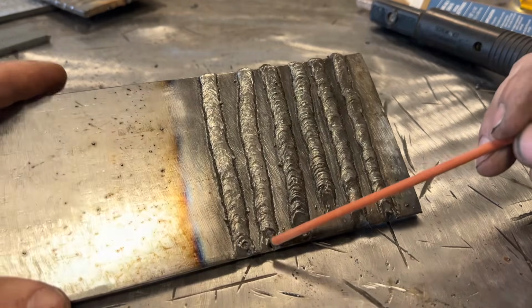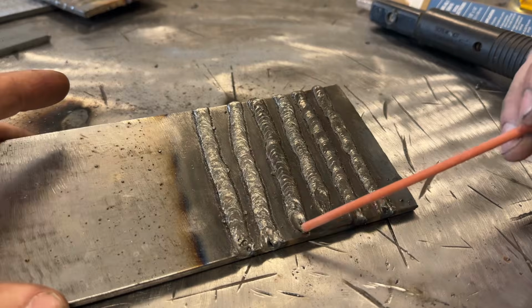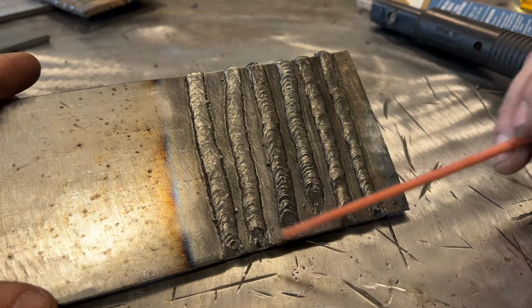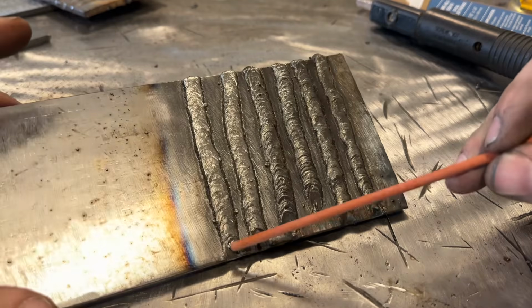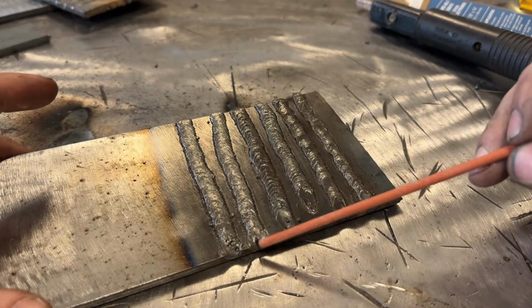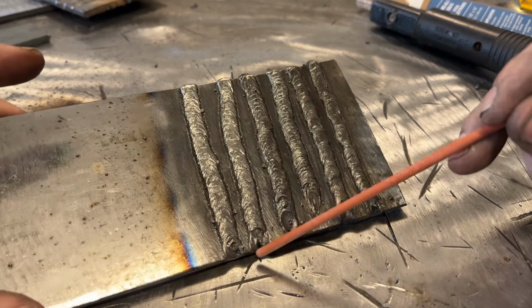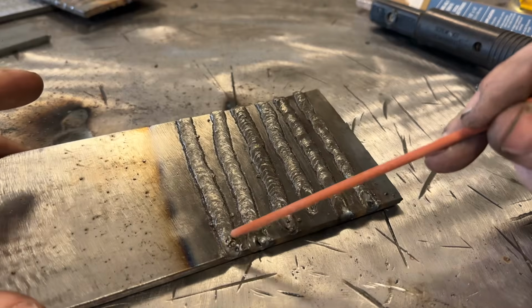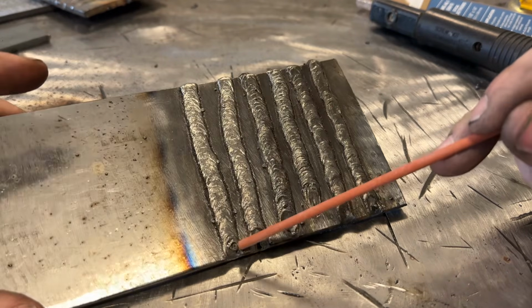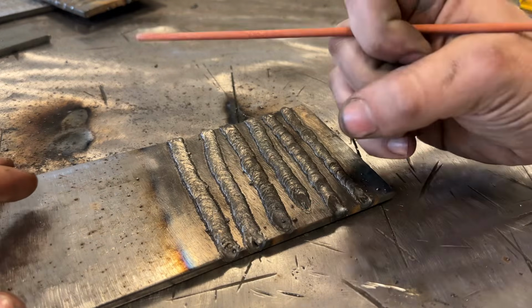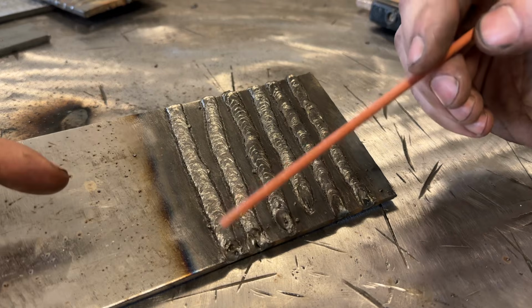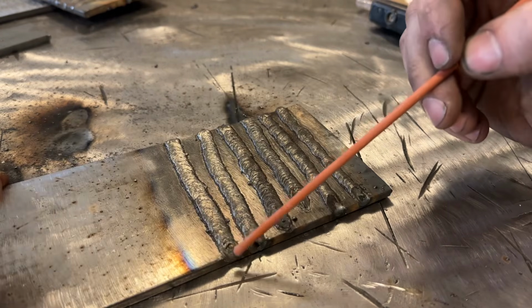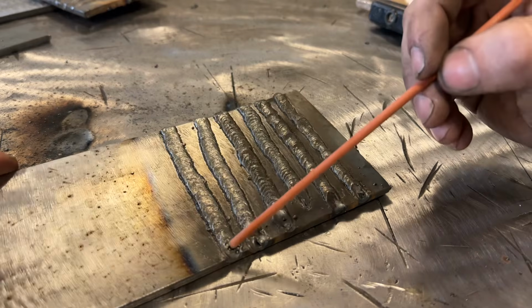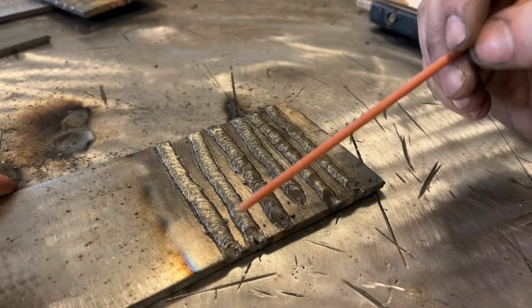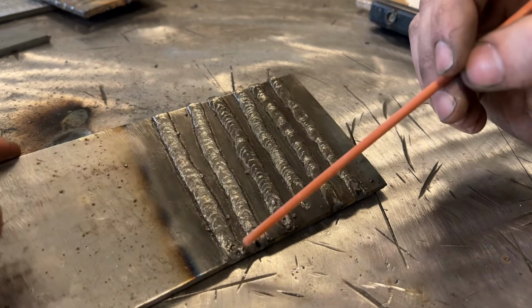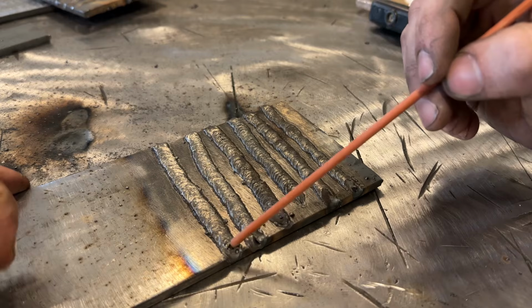You also see at the end, one of the things with 6010, it's very common, not so much up here, I didn't do it in these, I didn't make it to the end of the plate, to get porosity, and I wouldn't even call this porosity, it's just like a cavern due to not holding the end and then coming back through to fill that. So I snapped out of the arc, and because that molten metal is so fast to solidify, there were still balls of molten metal coming off the rod hitting this, and it essentially forms like a crater, much like an asteroid hitting the Earth. So I believe that's what you're looking at there, simply molten metal dripping off the rod into this pool, and it solidified so fast it just captured that.